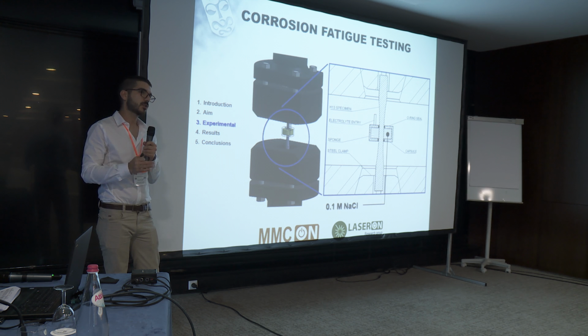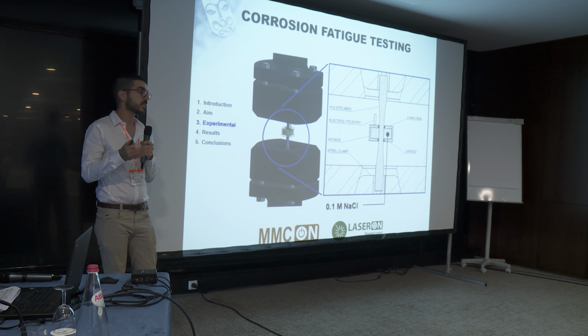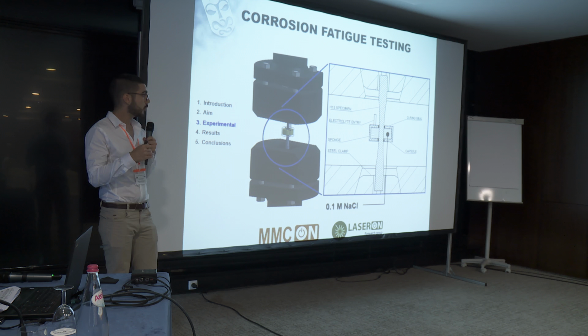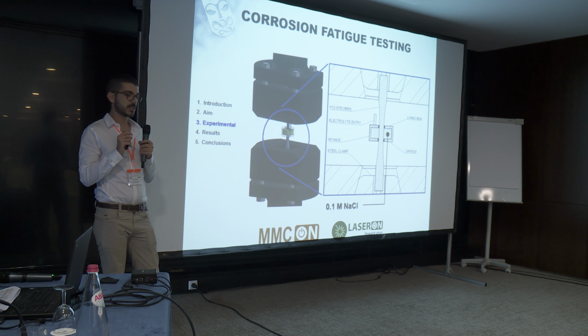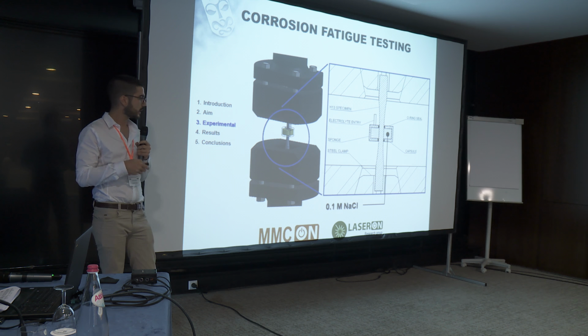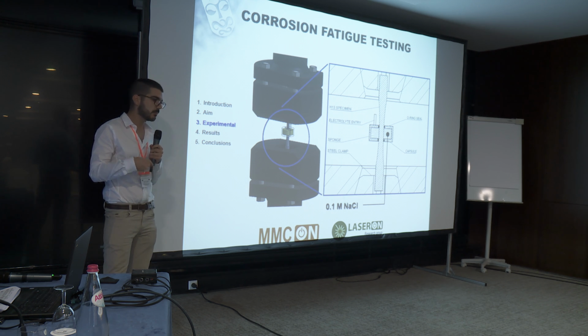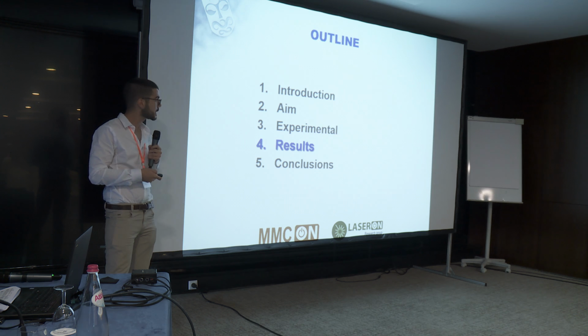Corrosion fatigue tests were done using the same parameters as described before, but we introduced this handmade setup where we introduce a sponge soaked with a 0.1 molar sodium chloride solution that was placed in contact with the specimen throughout the whole fatigue test.